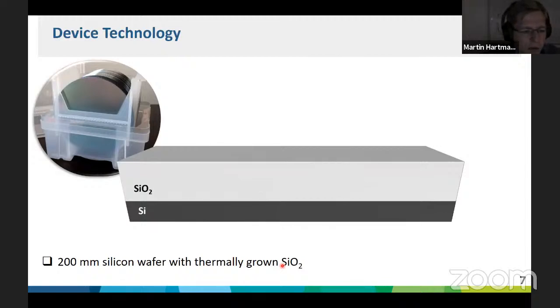So we work with 200 millimeter silicon wafers. In literature, the biggest wafer size that I saw in publications was around 100 millimeter wafers, so 4-inch wafers. But we work together with some companies and some other semiconductor fabs. And for them, it's really mandatory to work with 200 millimeter wafers to combine our technologies there. And this has a big advantage because then you fabricate a lot of CNT FETs in parallel. You can add a lot of variations during the processing to really optimize the devices.